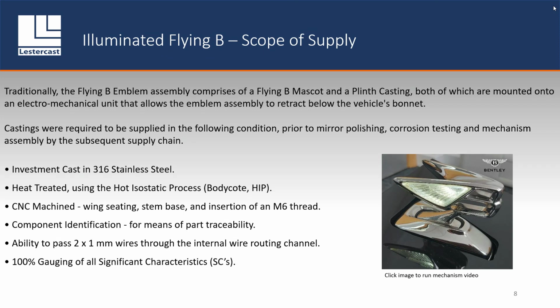And the real challenge when we got into the technical stuff was they wanted an internal wire routing channel that you see from this section here. It's 3 millimeters by 6 millimeters, which takes two 1 millimeter wires from the illumination on the inside down into the battery area. So as a casting goes, that was the challenge. We knew we could produce polished emblems, but could we actually produce one with an internal wire routing channel? And of course, Bentley put SCs on the drawing for control of significant characteristics. So we've got a number of gauges in place for series production to control those particular features.